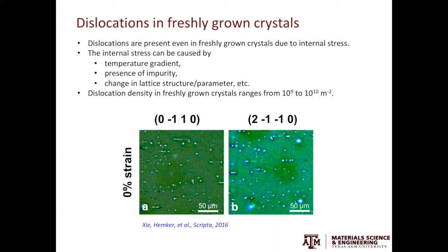Before moving on, I want to quickly say something about dislocations formed due to the change in lattice structure or parameter. These dislocations are widely observed in the thin films grown using the epitaxial growth technique. If the difference of lattice parameters is large enough between the substrate and the thin film, interfacial dislocations or misfit dislocations will form to accommodate the differences in the lattice parameter of the substrate and the thin film.